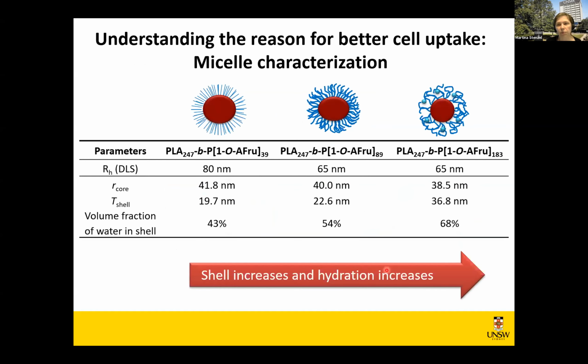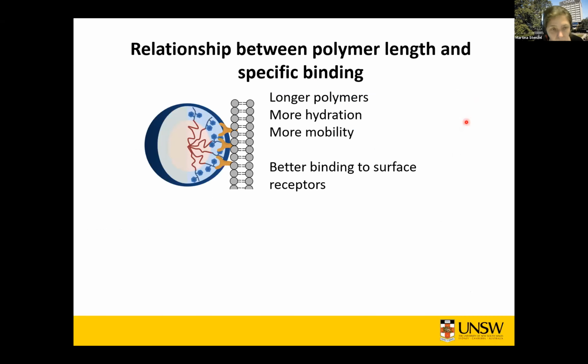In order to understand it a little bit, we have to dive deeper into understanding what the structure of these nanoparticles is. One way of doing that is, for example, neutron scattering or X-ray scattering. What neutron or X-ray scattering tells us is, for example, how hydrated the shell on the surface is, and how mobile these polymers on the surface are. And what we find here is that the longer the polymer is, the more mobile these polymers are. And by having a higher mobility of these polymers, we allow a better interaction with the lectins on the surface. So it basically means if we pack polymers very, very tightly, they're almost like a really tight toothbrush arrangement.